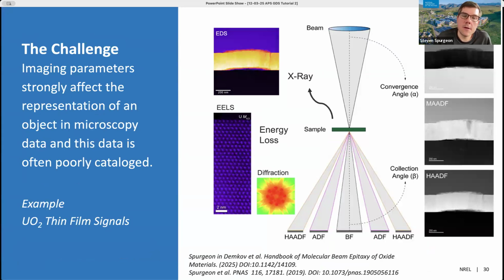The challenge of machine learning is that we need good training data, as I mentioned. And in microscopy in particular, imaging parameters strongly affect the representation of an object in data. So this is an example of imaging, just shows kind of what scanning transmission electron microscopy imaging looks like. We have a convergent beam that is focused onto the entrance surface of a sample. The sample is typically less than 100 nanometers thick. The electron beam is scattered through the sample, and then we have a variety of different detectors, both below and above the sample, to generate different types of imaging, spectroscopic and diffraction signals.